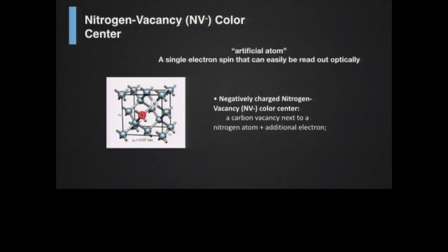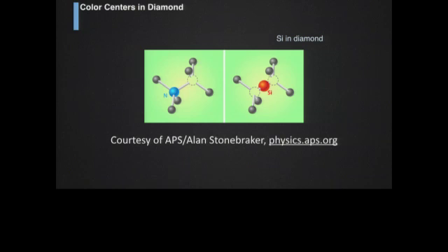One of the big interesting centers, of course, is the NV center, and that's the artificial atom, a single electron spin system that can easily be read out optically. Most of you already know a whole lot about that. But one thing that we've been working with is, instead of using nitrogen, we can replace the nitrogen with silicon. What happens with the silicon is that it creates a symmetric two vacancies on both sides, and that sort of cancels out the phonon response and produces a single photon, single electron type level. You'll see that when we show you some of the photoluminescence data. The same thing occurs for germanium, and the wavelengths associated with these are slightly different.